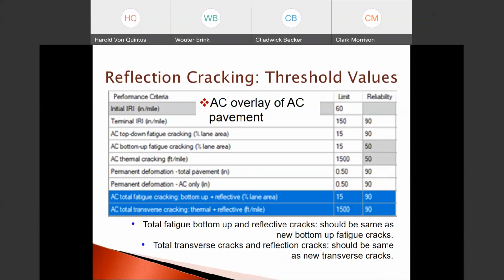The first are the threshold values, and I just want to make a few statements about the threshold values, specifically related to reflection cracking, or as shown at the bottom of this slide in blue, AC total fatigue cracking, bottom up and reflective, and AC total transverse cracking, thermal and reflective cracking in feet per mile. Some agencies use a different threshold value between total fatigue cracking and reflective, as opposed to new bottom-up fatigue cracking, as shown on the third or fourth line down at 15%.